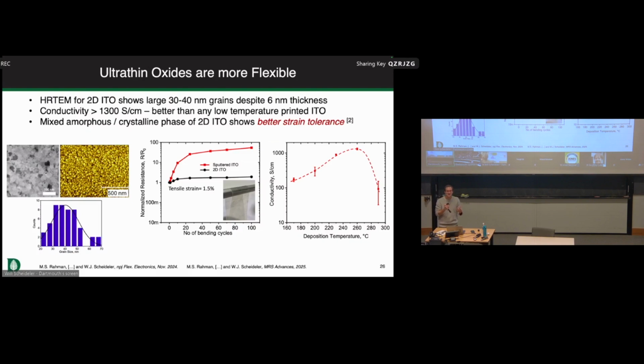The large grain aspect is something important to us because in a lot of cases in these materials, one of the main dominant scattering mechanisms is when an electron is scattered from the grain boundary. So if you have a larger grain material, in total you have a smaller effect from that grain boundary scattering.